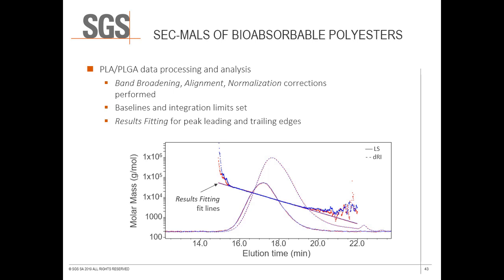This allows for the use of the refractive index data, which indicates the presence of sample molecules where the light scattering signal is too low to calculate realistic values. This is particularly useful for low molar mass species. As you can see, 5% or more of the peak would have to be excluded from integration if only realistic molar mass results were to be used without results fitting. In this case, only material greater than 2,000 grams per mole could be analyzed without results fitting.